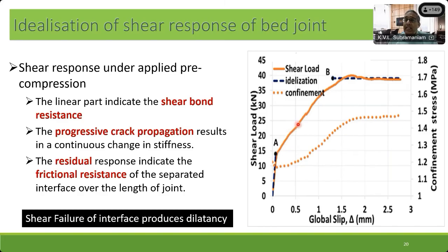Here is where a crack starts to form at the interface between the two bricks. As the crack starts to form, the slip starts to increase dramatically, but the load doesn't increase so much. Or I should say, the slope of the load versus global slip line sees a change. And this is very typical of a crack forming in any brittle or quasi-brittle material. Then eventually the load levels off.